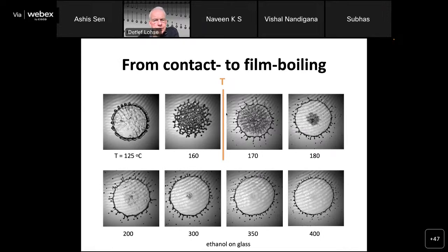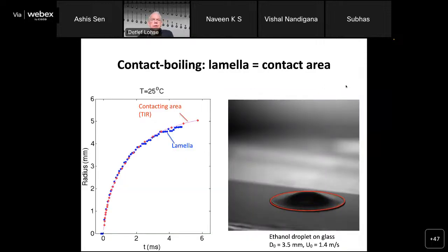So here I show you a typical snapshot as a function of the temperature for ethanol on glass. Up to here, you are in the contact mode, and here you are in the no contact mode, so in the Leidenfrost mode here. So this is how things depend. I mean, here in the middle, you still have some little contact, but you have the lamella, and here at 400, no contact whatsoever. So let's look into the correlation between what we see from the side and from the bottom.